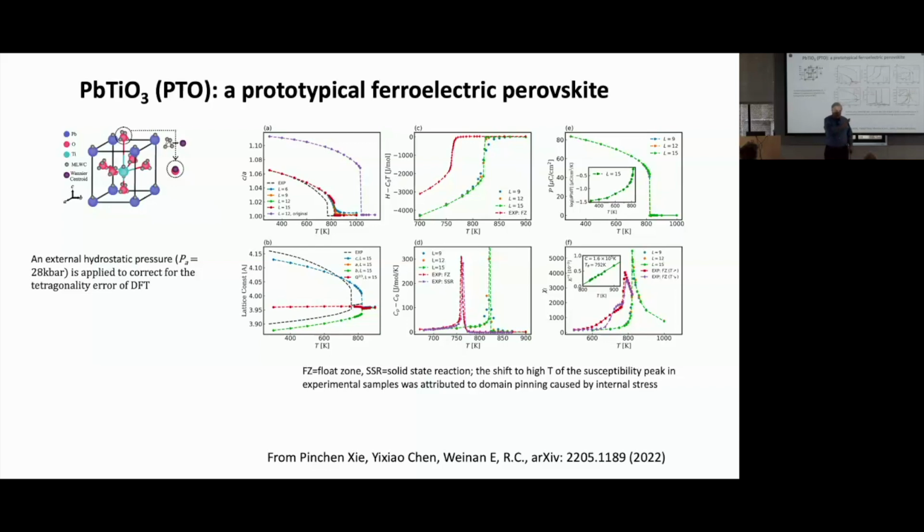Now, at this point, this is just classical. This is classical MD. We generate configurations, so there is a classical kinetic energy associated with the atoms. And in the training configuration, there are T=0 configurations, but also finite temperature configurations that are extracted from a molecular dynamics trajectory on a smaller system, like the 3x3x3 that I mentioned there.